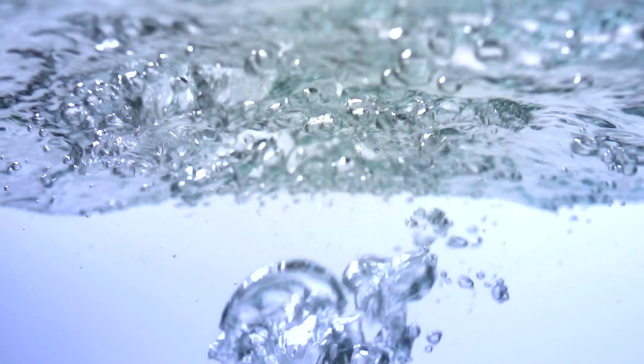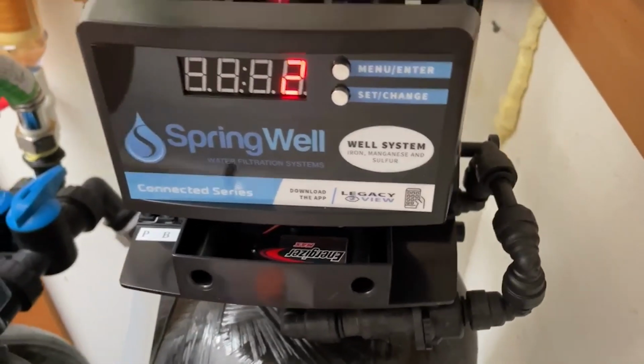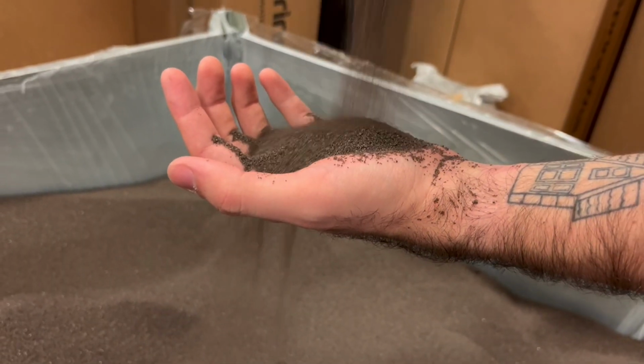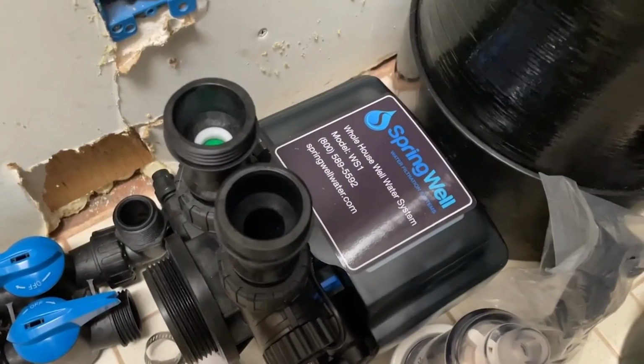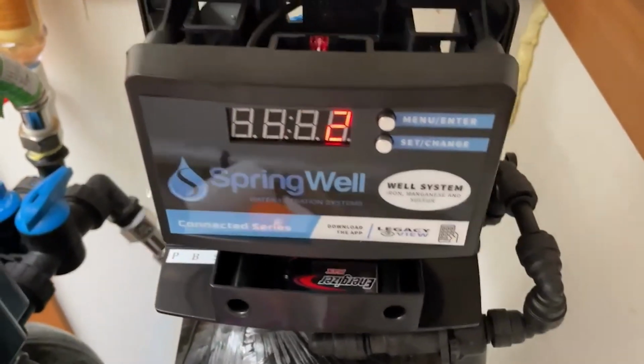An air injection oxidation, or AIO system, is another popular choice for removing ferrous iron. This system injects air into the water, converting dissolved ferrous iron into its solid ferric form. The oxidized iron is then filtered out using a media like manganese greensand. Some AIO systems can handle up to 15 milligrams per liter of iron, but again, efficacy is dependent on pH. This time, the system oxidizes iron better with a pH of 7.2 or higher. Plus, it's chemical free, which makes it a great option if you're looking for a more natural solution that won't affect water quality.